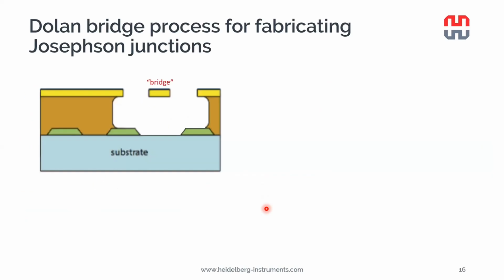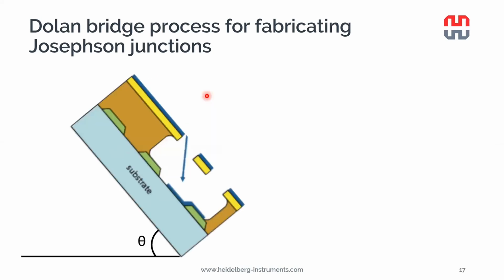And another process that takes advantage of freestanding bridges is the so-called Dolan bridge process, that is very widely employed in fabrication of different junctions for quantum computing applications, for example. Here we again start by defining a freestanding bridge. And the trick here is that we carry out evaporation with an angle. So we apply a tilt into the substrate during the evaporation of metal, and in this way we can evaporate metal underneath the suspended bridge.